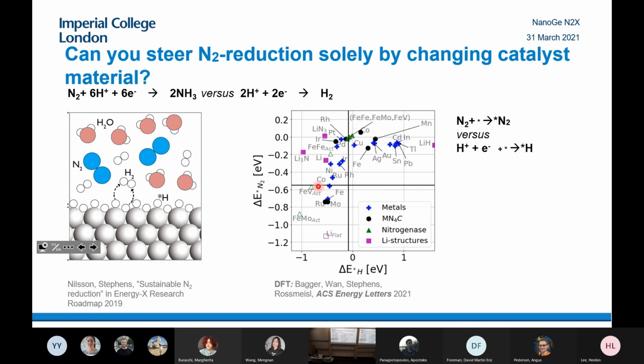So all the catalysts are either up here, so things like gold, they bind nitrogen and hydrogen weakly. This region, they bind hydrogen weakly and nitrogen weakly, or in this region, even nitrogenase, it binds nitrogen. So nature's catalyst for nitrogen reduction binds nitrogen strongly, and it binds hydrogen strongly. So this means that to circumvent this, nature's found another way, and you have to go beyond just solely looking at the catalyst material. You actually need to tailor the environment. It turns out it has a hydrophobic environment around it.